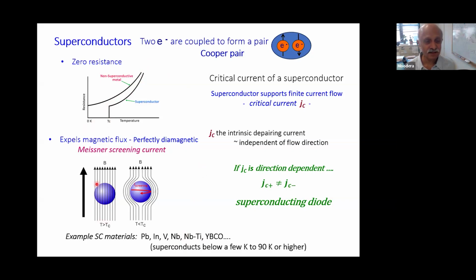The second thing is, if a magnetic field is applied before you cool down, then while you cool down below the TC of the material, it completely expels the flux. It creates what's called the Meissner current. It actually creates a field flux which is opposing the applied flux. As a result of that, in the middle, you have no magnetic field. This can only be there up to some magnetic field. Beyond that, of course, it becomes normal. So these are some of the hallmark properties of the superconductor.